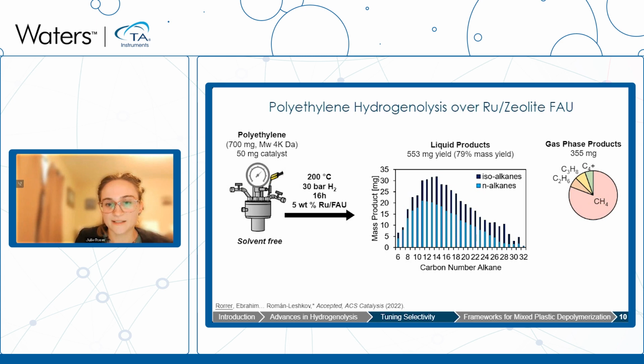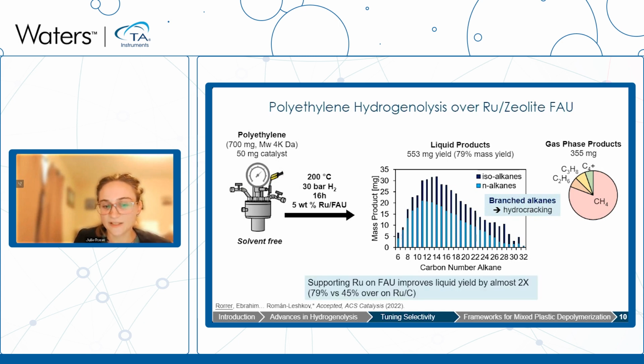But what's really exciting is that we see both linear and branched alkanes here. And these branched alkanes are a sign that we have the hydrocracking mechanism at play. And by supporting the ruthenium on this faujasite, by having this bifunctional catalyst, we increased our liquid yield by almost 2 times, so 79% compared to 45% over the ruthenium on carbon.